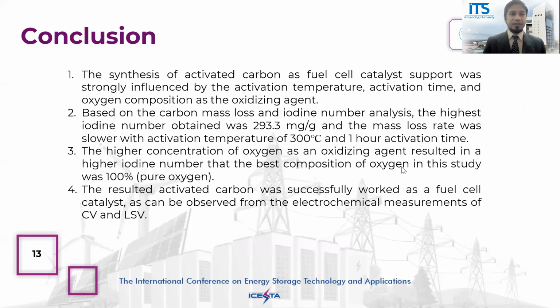In conclusion, the synthesis of activated carbon as a fuel cell catalyst support was strongly influenced by the activation temperature, activation time, and oxygen composition as the oxidation agent. Based on the carbon mass loss and iodine number analysis, the highest iodine number attained was 293.3 milligrams per gram, and the mass loss rate was slower with activation at 300 degrees C and 1 hour activation time. The higher concentration of oxygen used as the oxidation agent resulted in a higher iodine number, that is, with 100% pure oxygen.